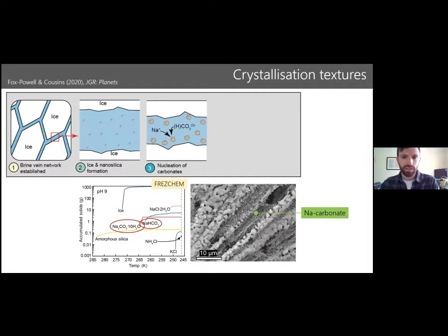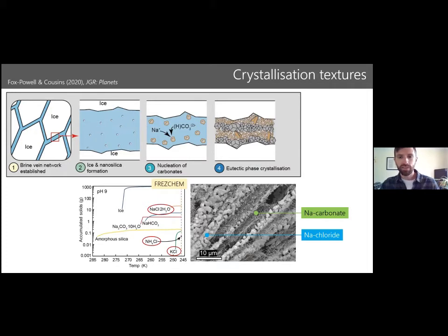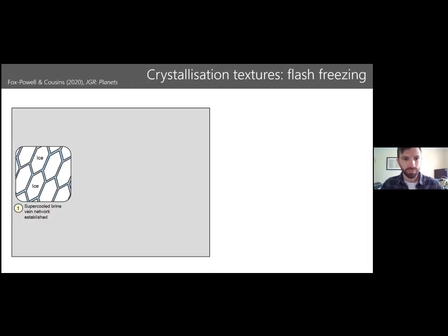Now, these were identified in our experimental samples as this population of really, really small crystals labeled here. So these are also likely just a slurry, kind of a suspension within the brine veins as cooling progresses. And it's not until later in the sequence, near the final stages of freezing, that we get chlorides like sodium chloride forming. These force their way through these crystal slurries and aggregate the whole system. So this is really a signature of these minerals forming in sequence and being able to spatially reorganize themselves.